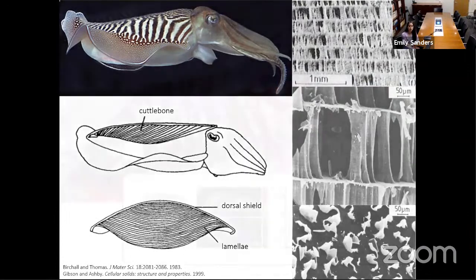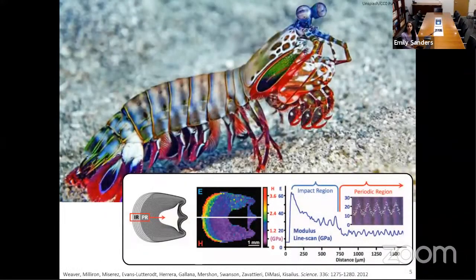In terms of spatially varying properties, there are many examples of biocomposites in natural systems. Here we have the mantis shrimp that has this club that sort of snaps to strike its prey with a large amount of force. And it turns out that biocomposites play a key role in the damage tolerance of this system. If you look here, you can see that the stiffness and the hardness are functionally graded through the cross-section of that club. And these authors here found that cracks tend to nucleate at the interface between these two distinct stiffness regions. And because of this abrupt change in stiffness in what they call the impact region, those cracks are prevented from propagating all the way to the exterior and you get some damage tolerance.